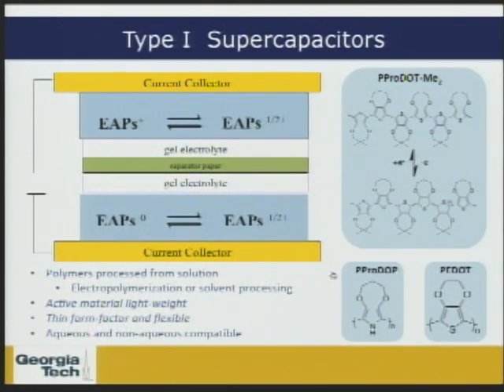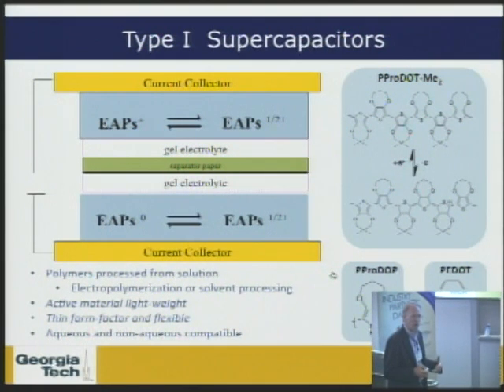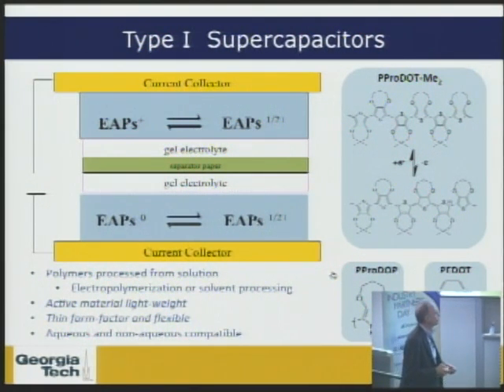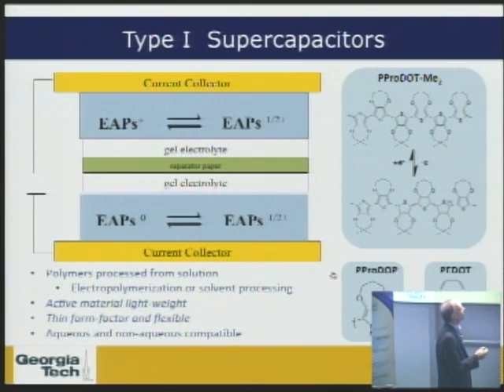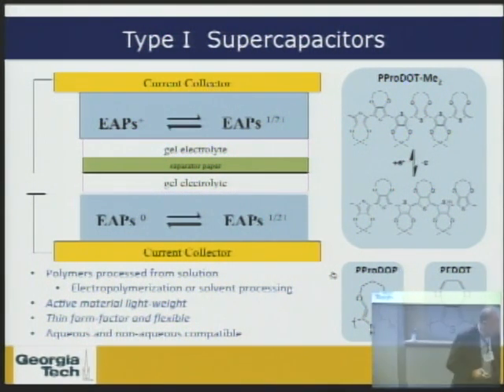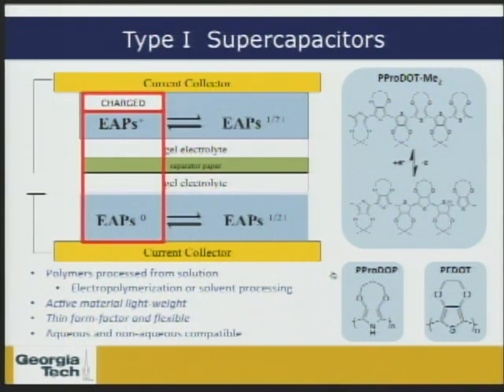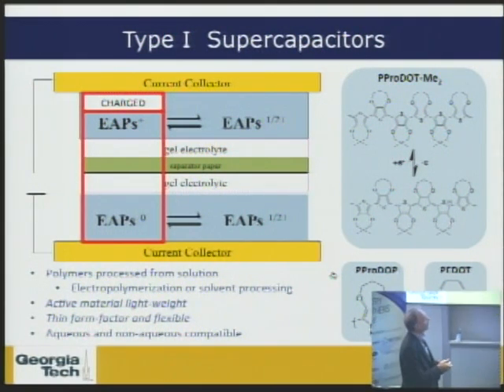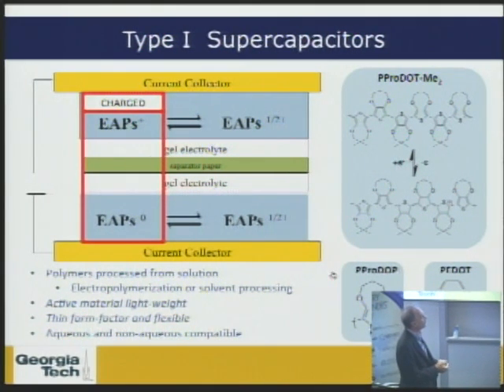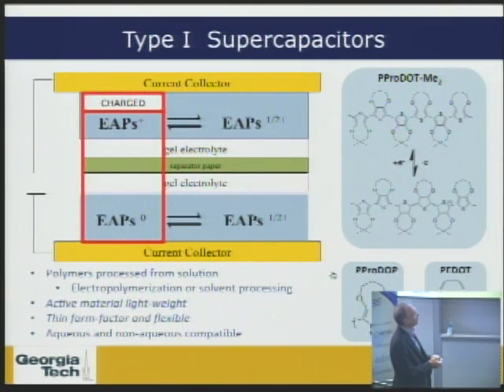Okay, so if we can control this level of charge transfer chemically, we can also do this electrochemically. And one way to think about using this then is to think about how we might use this to store charge. And so you can imagine we have a current collector with an electroactive polymer deposited on there. And we can set that electroactive polymer in its charged state or its doped state, and then have another electrode where we have that same polymer, for example, in its neutral state. And if we create an electrochemical device, we have a voltage or electrochemical potential between these two states.